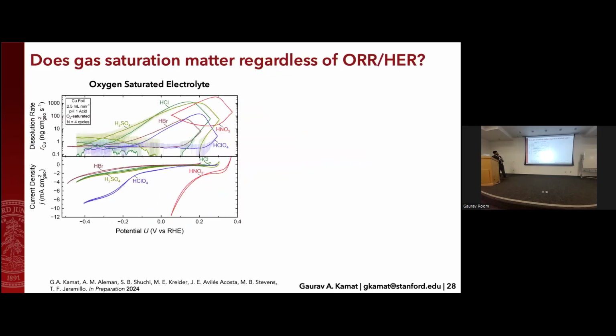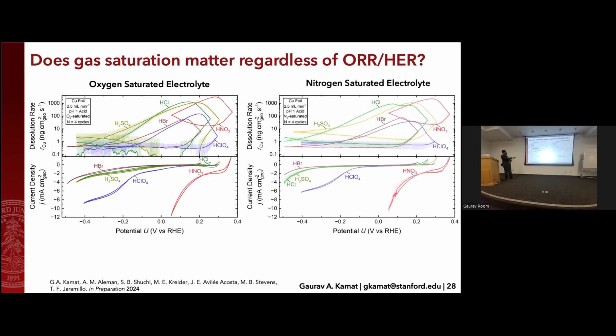Now, another thing we can study with this is gas saturation. I mentioned we had an electrolyte reservoir, and you can choose to put either oxygen or nitrogen in that system. So in oxygen-saturated electrolyte, this is copper foil in a variety of different electrolytes. You can see what's going on here in terms of the activity. If I switch this and I now sparge it with nitrogen, one, you see all of this oxygen reduction current